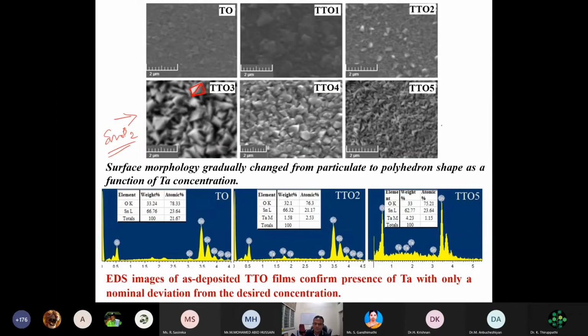And also we can do the compositional analysis by EDX, energy dispersive X-ray analysis. This will give you the presence of tantalum. So you can see that tantalum is also present in the film. Because it's spray pyrolysis, if you don't maintain the preparation parameters properly, sometimes these vapors will go out of the system. They may not even fall on the substrate. So the tantalum content may not be there inside the film to the expected level. So it is important to identify whether the percentage of tantalum is there or not.